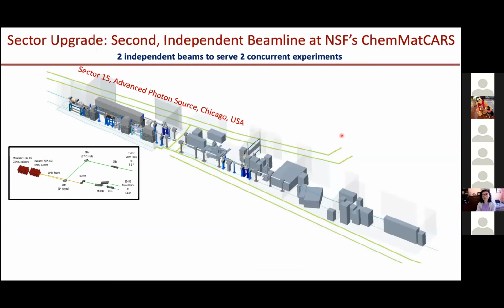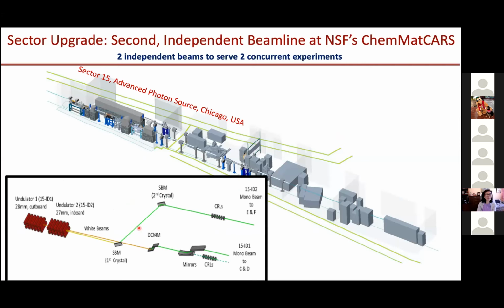Because of strong demand from our user community for more beam time and new techniques, NSF recently funded us to construct a second beamline that will be up and running hopefully in 4 years. The 2 beamline optics are shown as follows. The straight line, which is the existing line, will be upgraded with new double crystal monochromators, so the energy range still can go between 5 and 70 keV. We also added 2 pairs of multi-layer crystals as our monochromator, just to enhance the photons at 20 keV and 30 keV.